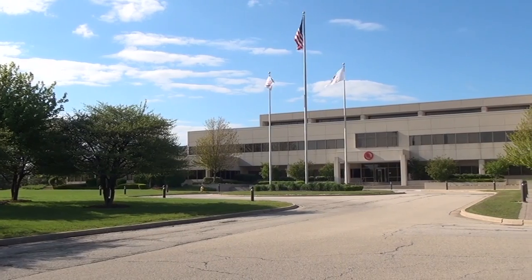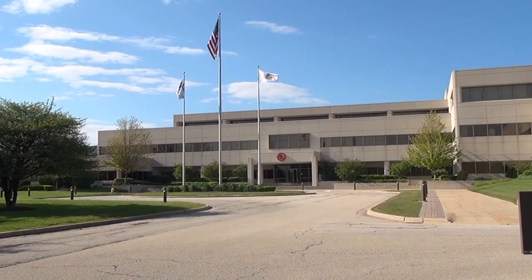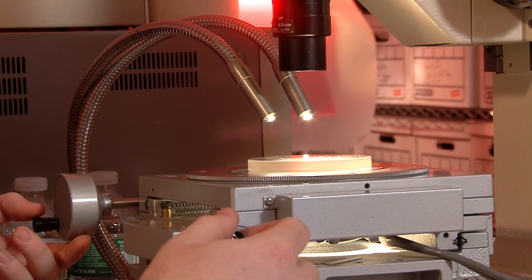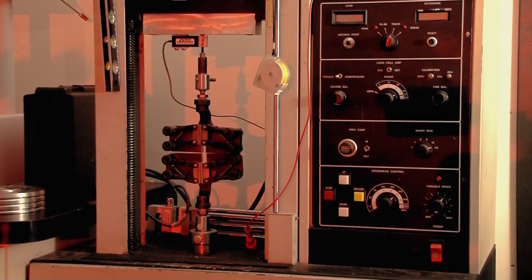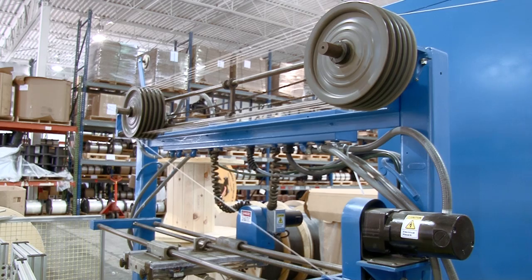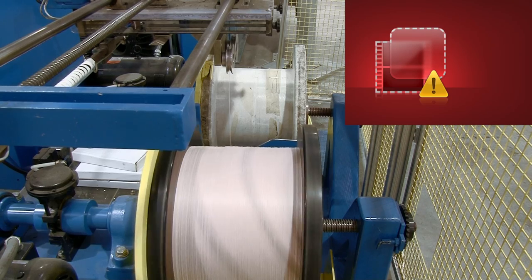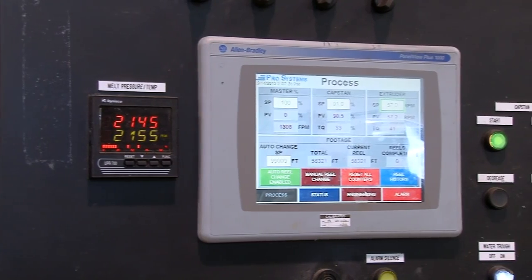At UL's Northbrook, Illinois Plenum Lab, CCG proved that fluorofoam wire insulation exhibits extremely low levels of flame spread and negligible peak and average smoke generation, while also delivering enhanced electrical performance and excellent crush resistance. Fluorofoam can provide a unique processability akin to a solid FEP extrusion. Running speeds of 1,600 to 1,800 feet per minute are readily attainable at foam rates of 25 to 55% for